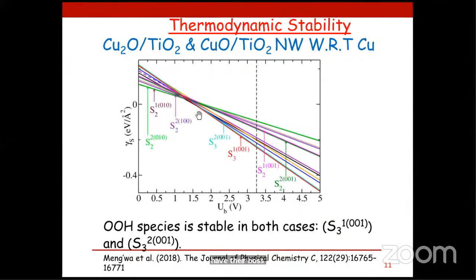For the oxides now, we have two oxides of copper on TiO2. S3 stands for the CuO over TiO2. Then S2 stands for the Cu2O over TiO2. So we see that at effective bias, which is actually equivalent to the energy gap of pristine TiO2, all the water oxidation species on CuO over TiO2 are more stable compared to those on Cu2O over TiO2. Again, when you go to the zero bias, the reverse is true.